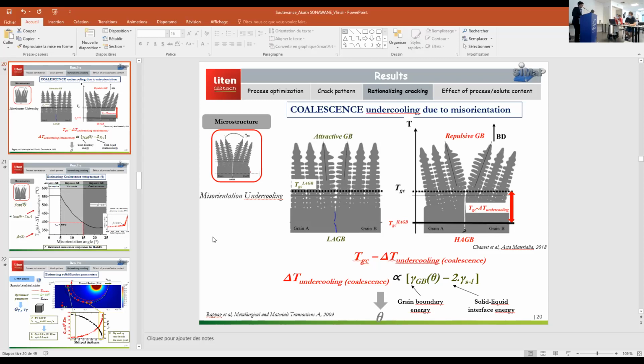So according to me, I have this feeling that the solid liquid interface energy, which is a very important aspect in the coalescence theory, is reported in a few publications I have seen by Professor Rappaz, that he has tried to change the composition of aluminum alloy with the help of zinc and some other elements. And he observed that there is a change in dendrite orientations, and this particular solid liquid interface energy is able to control the anisotropy of the growing dendrites. And according to my feeling, this is what I think, but probably it might not be true.